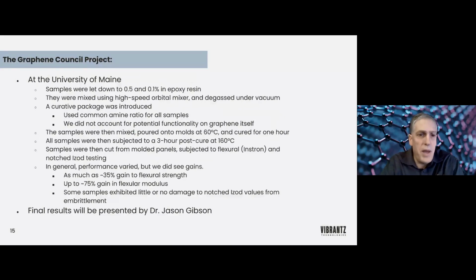So at the University of Maine, the samples were let down to two specific loadings, 0.5 and 0.1% in epoxy resin. They were mixed using a high-speed orbital mixer and degassed under vacuum, and a curative package was introduced. And we used a common amine ratio for all samples. So we didn't adjust for any stoichiometry that might have existed on the graphene or any functionalization that occurs. We treated all the graphenes exactly the same.